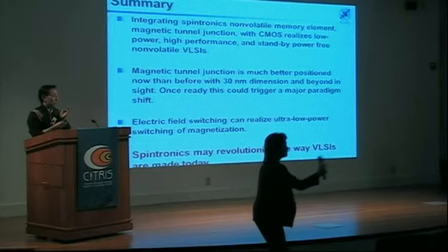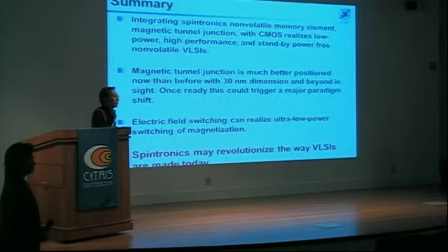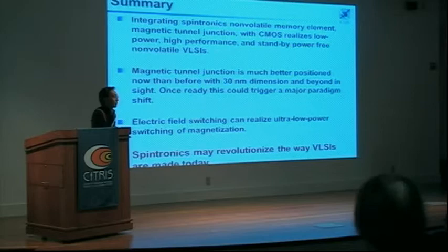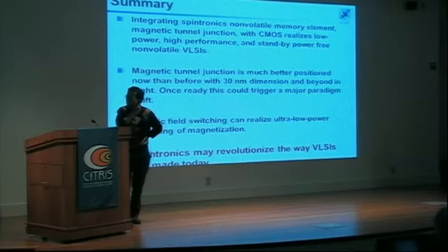I just have a question about the scalability. Based on your experiment, which is the state of the art, the diameter of the magnet is 40 nanometers, and the stability was 40 kT, which is on the lower bound. If you decrease the area, then we are going to lose the stability clearly. I saw you show that 5 nanometer grain size, but you didn't talk about the stability, and I know in hard disk drives for that small grain size, the coercivity is really high. They use, for example, heat assisted or microwave assisted methods to flip the magnet. I just want to get your opinion.